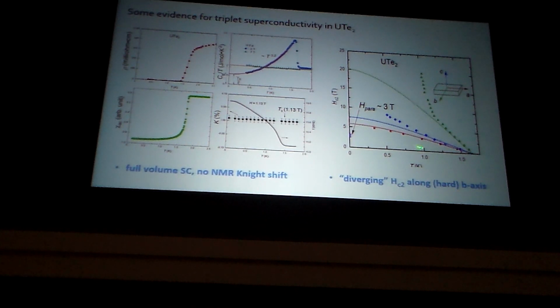The other suggestion for that is the critical field itself. So if you measure the magnetic critical field, and they did it in 3 different directions, a typical s-wave superconductor will have a limit called the paramagnetic limit. It's the field at which you would flip the spins. At that field, you basically destroy the pairing. However, if it's a triplet, you don't. And so the critical field can get much, much higher. So this is some fairly convincing evidence that it's triplet, but of course more work has to be done.